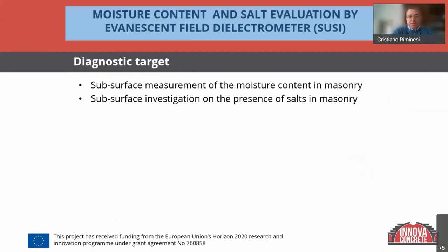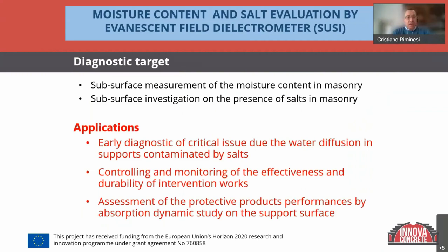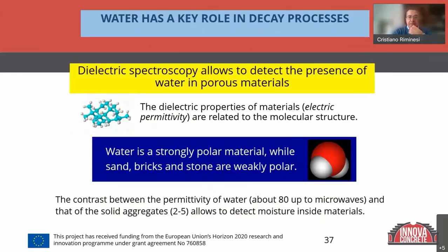In order to understand the behavior in depth, we need to perform a subsurface investigation. This kind of investigation is possible with this device, and we can perform the measurement up to two centimeters in depth in the substrate. The principle of this measurement is to detect the dielectric constant, a particular property of the material. Water inside the host medium, in this case concrete, has a very different value: concrete has a dielectric constant of 2.5 versus 80 in the case of water.